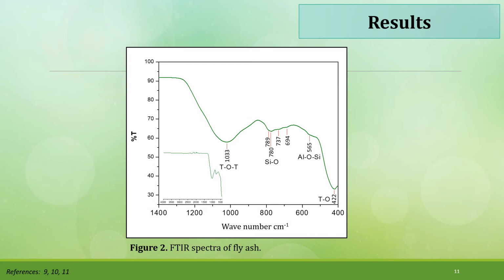The FTIR spectrum of fly ashes exhibits two main broad and intense bands, characteristic of internal vibrations of silicon and aluminum tetrahedra. The characteristic bands of quartz, mullite and amorphous material overlap in the 1200 to 900 range, generating the broad and intense band in the FTIR spectrum of fly ashes. Gaussian deconvolution of the spectrum revealed 5 fundamental signals. The series of lower intensity bands located at 1109, 790 to 780 and 694 are characteristic of quartz, while mullite is responsible for the bands at 1173 and 560 to 550, associated with octahedral aluminum. The bands located at 984 and 928 were attributed to the amorphous phase.